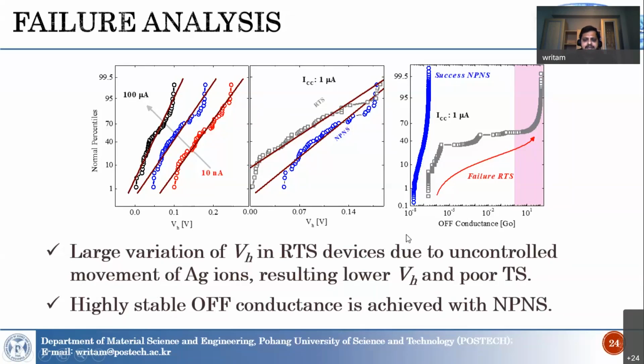However, the stability was also limited to some extent. So further work was done with the alloy electrode, silver tellurium, and also some other alloy electrodes. With the silver tellurium alloy electrode, if we have a fair comparison with plain silver, normally for silver devices there is always a possibility to increase the conductance towards the higher side, meaning the filament can grow over the switching process. But with this scheme, the silver tellurium is showing very stable behavior, close to 1G0 conductance level. So the failure probability of silver devices is always stuck to the on state, while the failure probability of silver tellurium is always stuck to the off state with this kind of scheme.